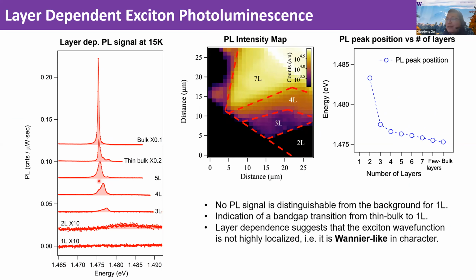Because for me, the intensity here is mainly determined by the electronic structure, either direct or indirect band gap. If it's indirect, how far the band edges are away from each other matters, right? Because if you want to emit light, you need a phonon to help. If they're really far away from each other, then the chance for them to recombine is lower. So electronic structure dominates.